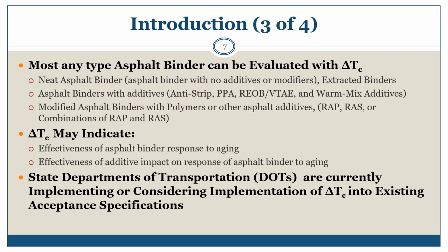Delta TC may be used to evaluate any asphalt binder. Examples include neat asphalt binder with no additives, asphalt binder with additives such as polyphosphoric acid, PPA, and refined engine oil bottoms, or vacuum tower asphalt extender, REOB, VTAE, modified asphalt binders that have been blended with polymers or asphalt additives, and recovered asphalt binder containing RAP, RAS, or combination of these with virgin binders.